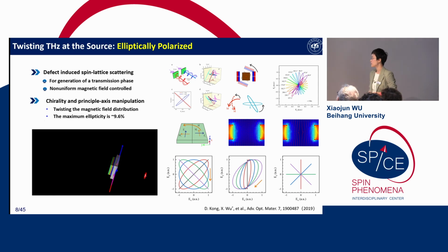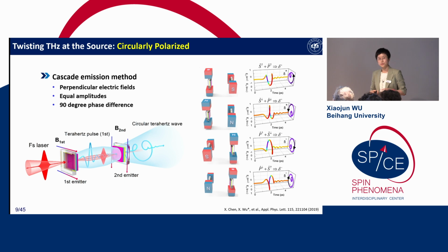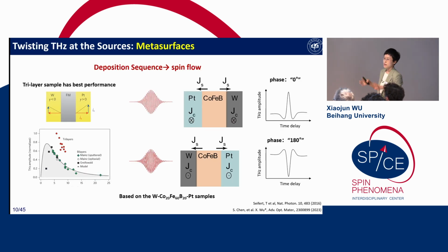And then we also used a cascaded method to recycle the residue pump light. For example, the first emitter absorbs only half of the pump energy, and we recycle the residue pump light. Then we use the phase difference between the first terahertz pulse and the second pulse to produce a perfect circularly polarized terahertz beam with this cascaded method. And these two methods are not so elegant.